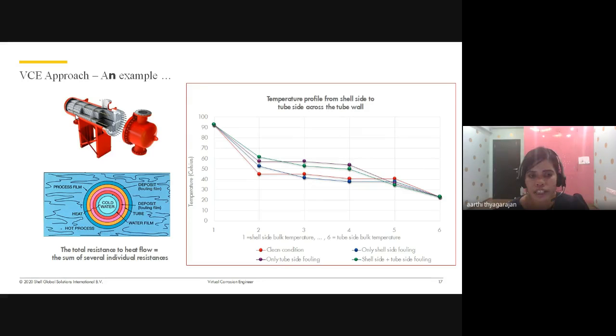The probability of occurrence for each mechanism is obviously affected by the quality of water treatment, but also by the operational conditions. Moreover, in most of the Shell assets, the water chemistry is considered to be managed fairly well. So hence we got a lot of clue on how the operational conditions could affect this, and to differentiate between the exchangers and identify those exchangers that are at high risk of failure. What we did in the VC project is to focus more on factors that are unique to each individual exchanger. So MIC, microbially induced corrosion, is more likely when the flow velocities are low, whereas erosion corrosion is highly likely when the velocities are high. Under deposit corrosion is more significant when the tube skin temperatures are high, and that's what you see in this graph on the right hand side.